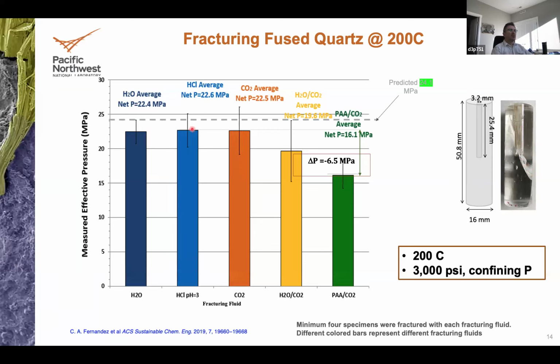And we thought that maybe it's the pH: CO2 is an acid gas, so it may reduce the pH. Is the decreased breakdown pressure with polymer solution CO2 probably a pH effect? No, it's not, because we added hydrochloric acid and fractured, and we got similar values, within the variability of the samples, to the breakdown pressure at which quartz or fused silica should break. The same for CO2. When we go to water CO2, we have more variability than the other 3, and also slightly lower pressures, about 3 to 5 megapascals lower. But when we use a polymer solution CO2, the pressures at which we fracture are even lower. So similar to what we see with the Kosovo samples, but now in a very homogeneous surrogate material like fused quartz.